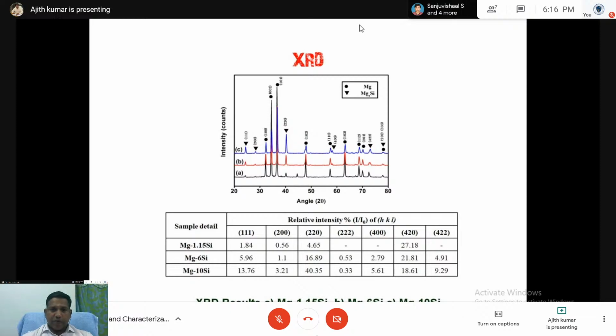This is a typical picture taken from our thesis, showing how the XRD changes with silicon addition. We add silicon lumps to the magnesium melt, mix it, hold it, and pour it into the mold. We got magnesium silicon alloys, but in the XRD there are no silicon peaks. All the silicon reacted with the magnesium, and we got Mg2Si phases. With silicon addition the intensity height is higher, because more Mg2Si is present in the material. In magnesium 10Si, the Mg2Si phase percentage is high, so the intensity value is higher. So we can identify which phases are present in a particular material using XRD.